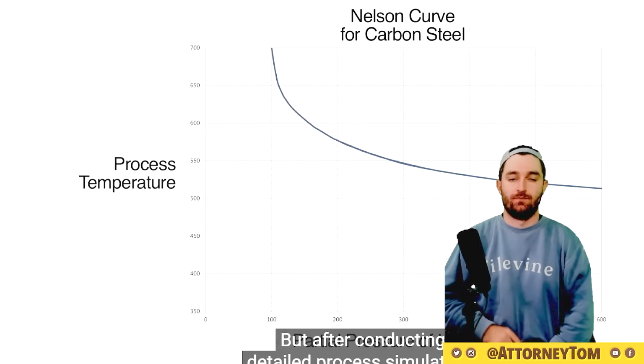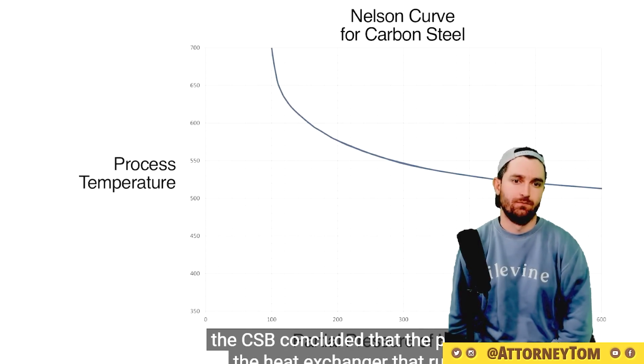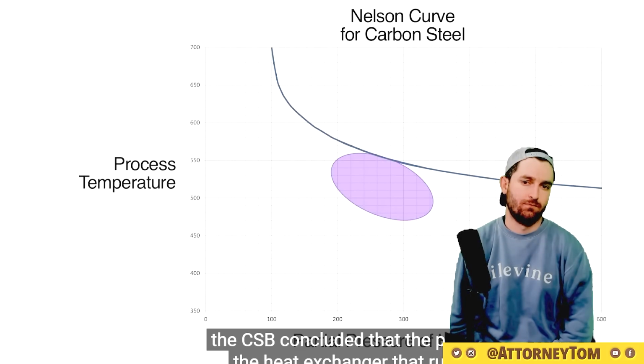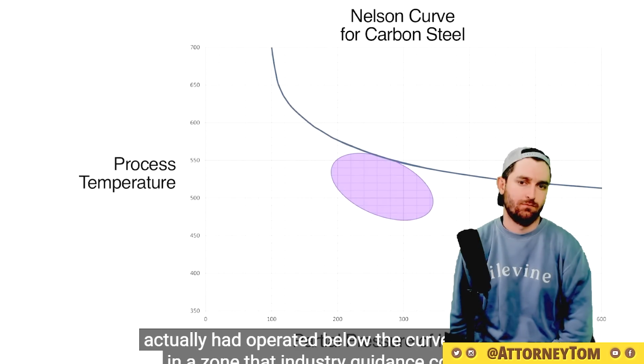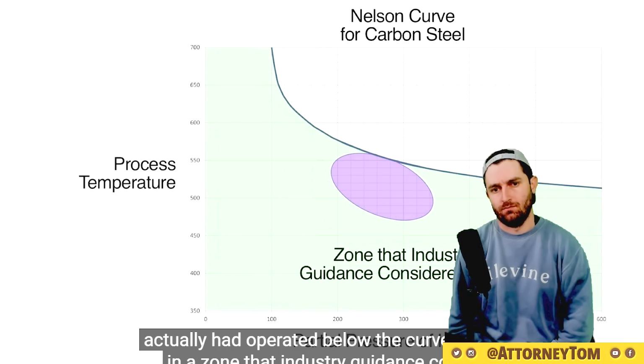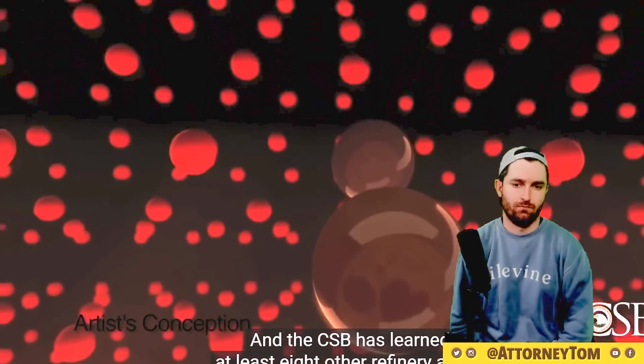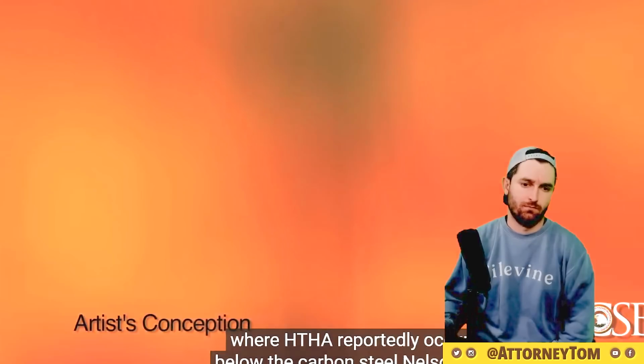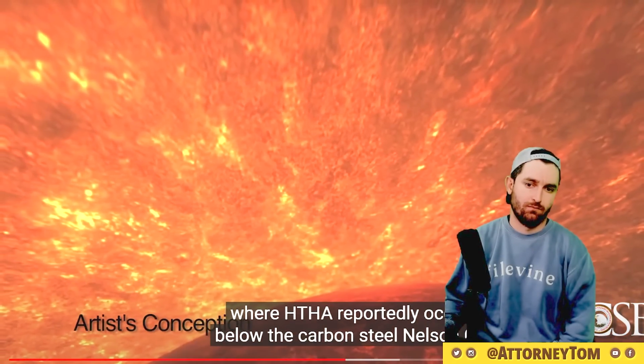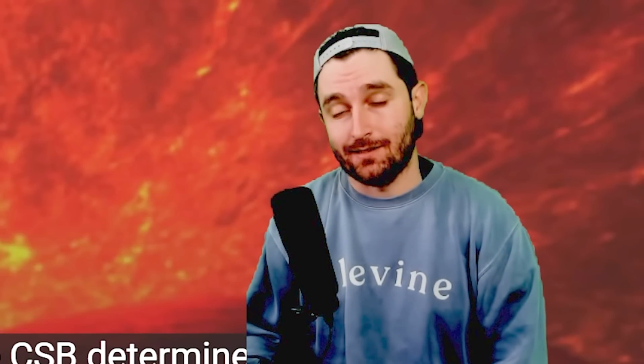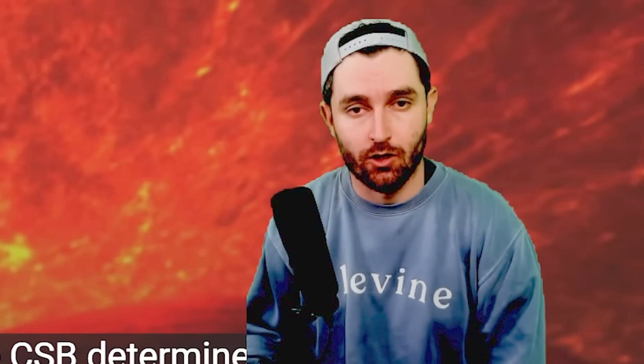But after conducting detailed process simulations, the CSB concluded that the portion of the heat exchanger that ruptured actually had operated below the curve for carbon steel in a zone that industry guidance considered safe. And the CSB has learned of at least 8 other refinery accidents where HTHA reportedly occurred below the carbon steel Nelson curve. So 8 other accidents that occurred below the Nelson steel corrosion curve. That tells me that curve is unreliable.